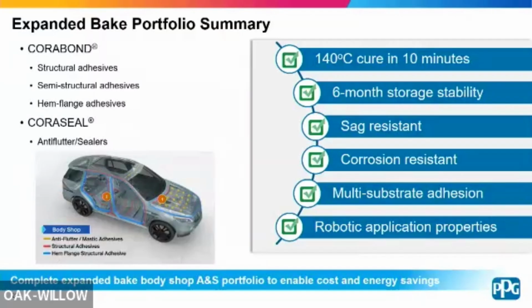So just to summarize, we do have a full expanded bake portfolio now, so CORABOND structural adhesives, semi-structural hem flange, as well as our CORASEAL anti-flutters and sealers, all of which can achieve that expanded bake window with that minimum 140C cure in 10 minutes and 6-month storage stability. And some other properties I didn't go into detail today, but that obviously are important too, would be sag resistance, corrosion resistance, multi-substrate adhesion, and then robotic application. So all of these products partner well with our new Ecoat developments to help enable those costs and energy savings that Paula mentioned in her part of the talk.